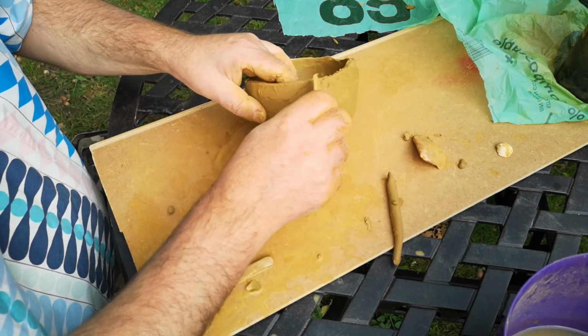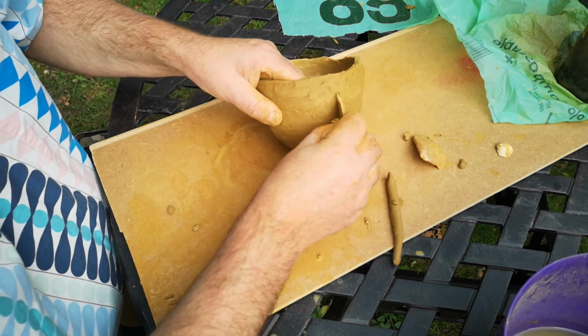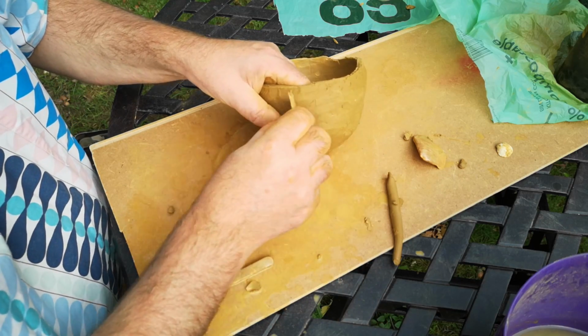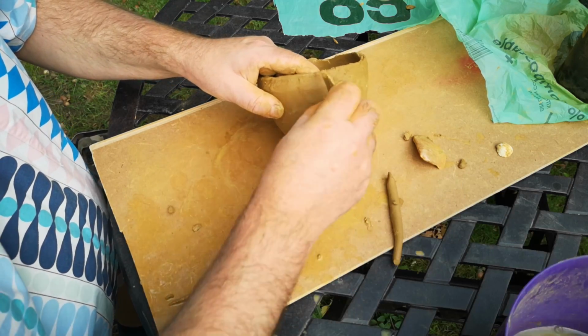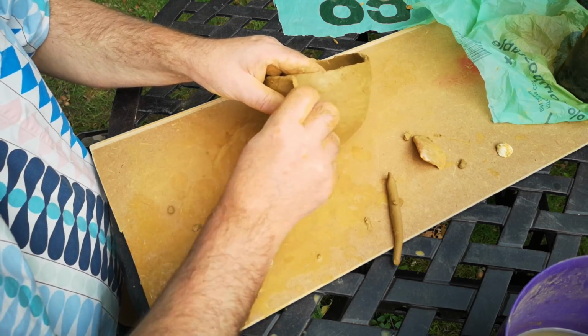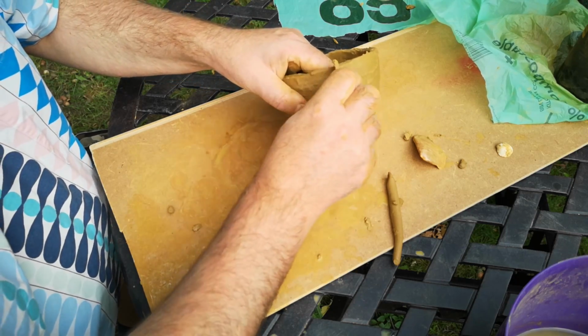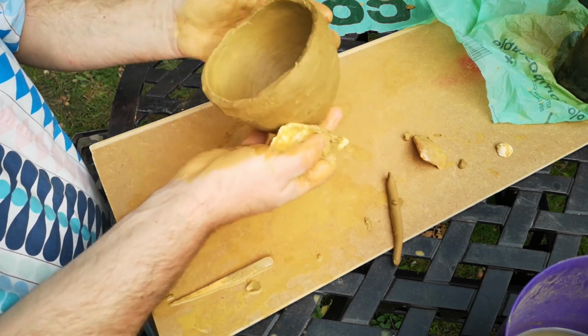Meanwhile, I've taken some time to digest the meaning of the firing failures from part 3 and consider my actions to remedy them. I've already begun making my next round of pots, of which hopefully I can get at least one fired intact, to take us onward to the cooking episode. Here's a sneak preview of one of them and a spoiler on a couple of the changes I'll be making. That is, thinner walls and no abrupt angles on the base or rim, just a continuously curved profile.